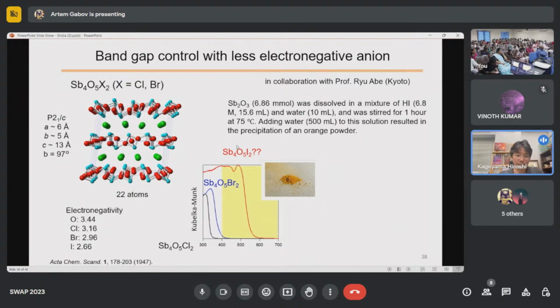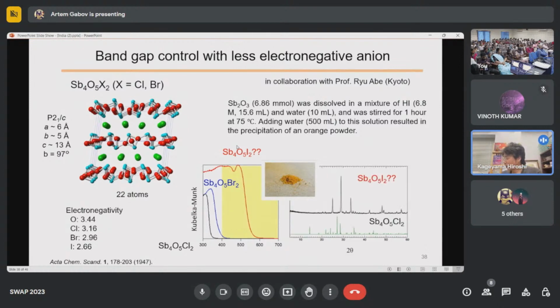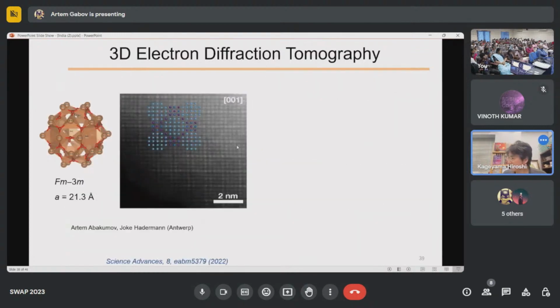So we thought that maybe we should prepare this unreported iodine-based material. Iodine has less electronegativity. And in fact, we observe in this red curve that the band gap is strongly reduced. So we expected that this Sb4O5I2 material, antimony 4, oxygen 5, iodine 2 compound, should be obtained. Okay. However, we couldn't index the X-ray diffraction patterns. And from the TEM diffraction pattern, we found cluster-like units in the structure and the lattice parameter seems to be much larger than the originally expected compound.